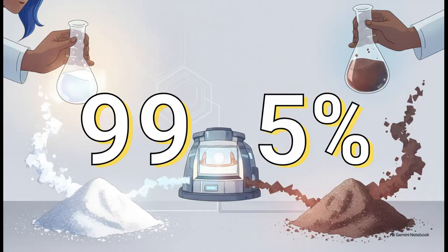But here is the crucial takeaway. You literally cannot just scoop up standard beach sand to make high-quality glass. No way. Premium glass-grade silica requires a minimum purity of 99.5%. If you have impurities in there, like iron oxide, which is super common in nature, it gives the glass a cloudy, odd-colored tint that completely ruins its optical clarity.